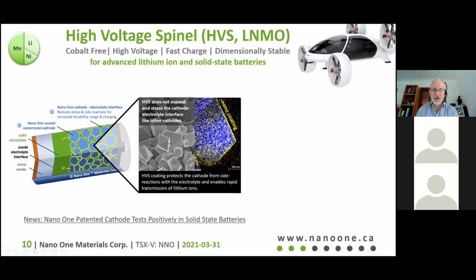This is a very nice picture of the crystals. If you blow this up, or have a very big screen, you can see that the surface of these crystals is a little rough. That's because, in the section through the crystal, you can see the same thing. The coating is 5 nanometers thick and comes to the surface of the crystal from the inside out. So we're not adding the coating on the outside of the agglomerate; we're allowing it to come to the surface of each individual crystal.